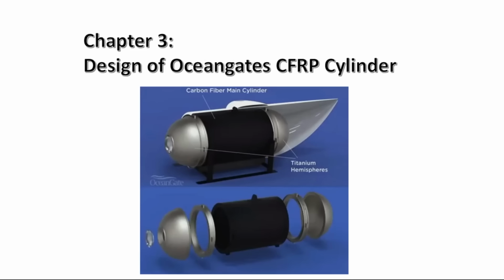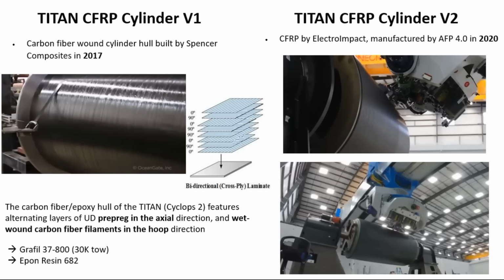The CFRP cylinder of the Titan was manufactured 2 times. The first version was built in 2017 by Spencer Composites. The carbon fibre hull of the Titan features alternating layers of UD prepreg in the axial direction and wet wound carbon fibre filaments in the hoop direction. The second version was built using automated fibre placement by Electro Impact in 2020.